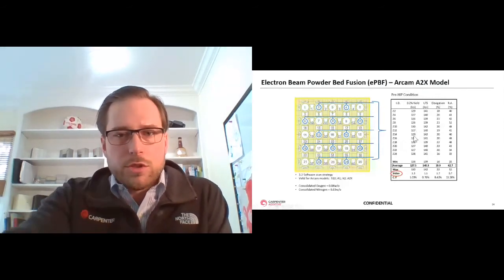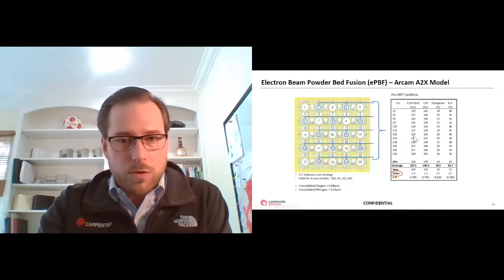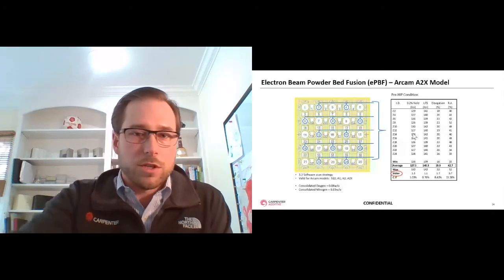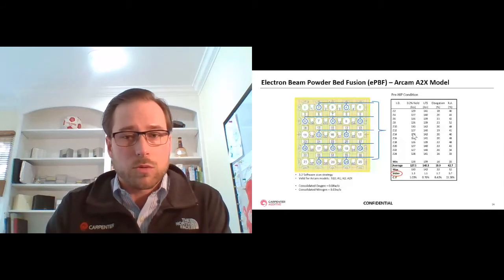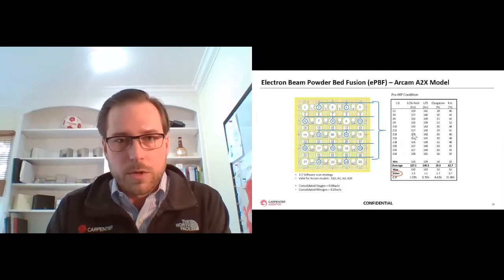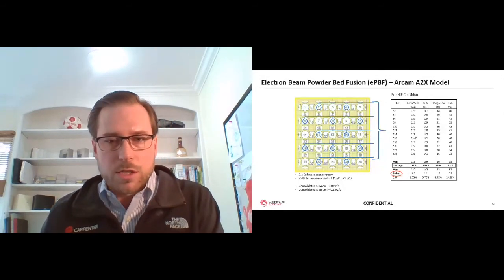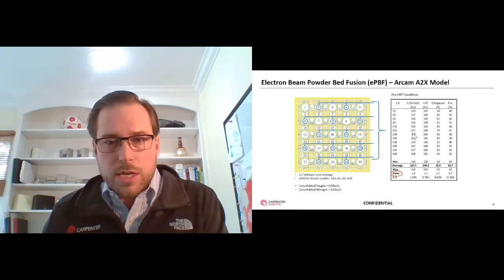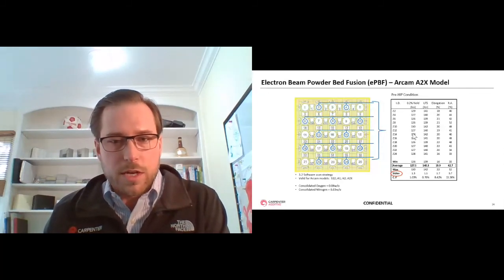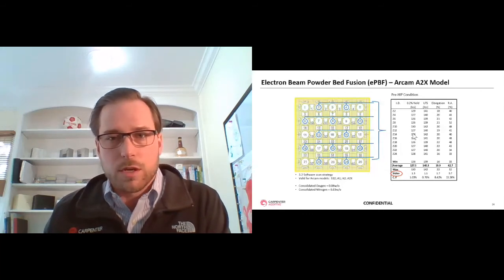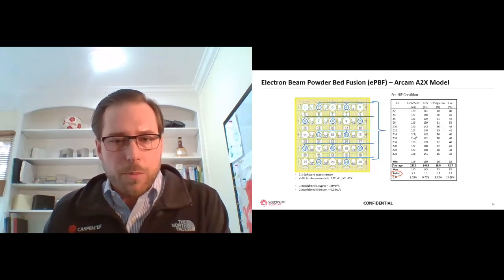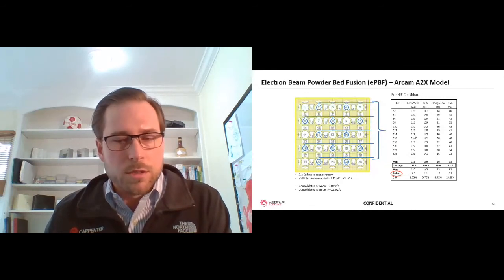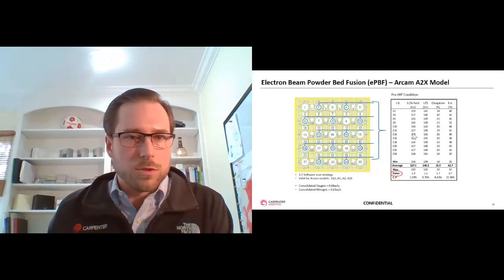And so what you'll see here is, I wanted to list all the results out, right? Rather than just showing an average and a standard deviation, I wanted to list all the results out to show you how small the amount of scatter is in these results, right? Across the build envelope. And so this is on an Arcam A2X, and you can see that your UTS, your ultimate tensile strength, you have a standard deviation of 1 KSI. Similarly, for a post-hip condition, right, you reduce that even further to a UTS of 0.7 and an elongation of 0.9. So really impressive in terms of scatter across the build.